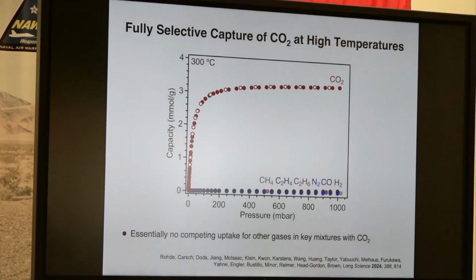If you take gas adsorption data, here's the result. Probably none of you are often looking at adsorption isotherms like this, but this is the most stunning gas adsorption data I've seen because of the temperature. 300 degrees C, huge uptake of CO2, it's fully reversible. So the filled circles in these plots are adsorption, where we're increasing the pressure. Open circles are desorption, decreasing the pressure. This is showing this huge capacity for taking up CO2 at 300 degrees C. It's never been seen before in a porous material. But you can just use vacuum to swing the CO2 off.